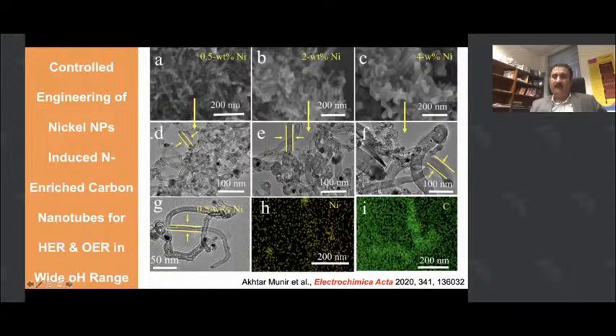We found these are really useful again to split water, and they were useful not only for OER, the oxygen evolution reaction, but also for hydrogen evolution reaction. So they are kind of dual catalysts, very useful for this type of application.